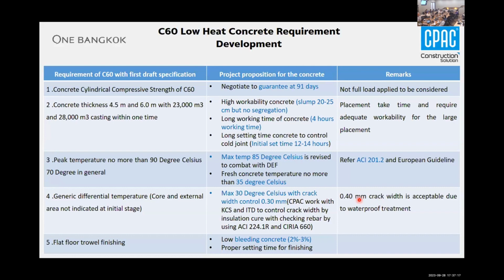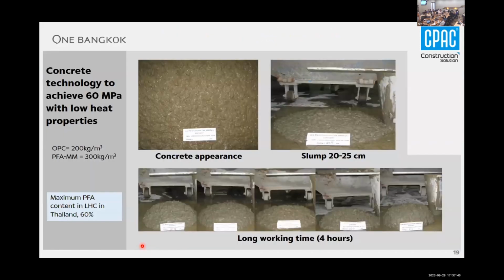The crack control for this project is around 0.4 millimeter acceptable, because after this, they are going to do a waterproofing treatment on the structure. And we need low bleeding concrete, because after they cast the foundation, they will trowel the surface to make a car park area, so they don't need to do a topping again. This is what we were working on. And you can see here, we developed the concrete for this one. We use 60% PFA or fly ash to replace the cementitious material. The cementitious material for this one is around 500 kilograms per cubic meter. And this is how the concrete looks.